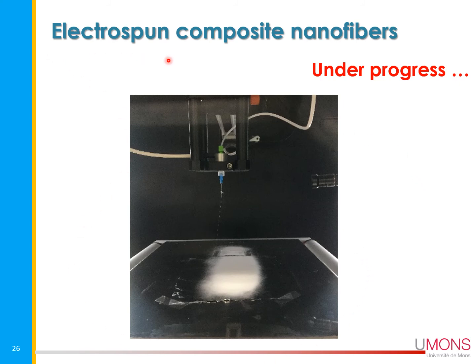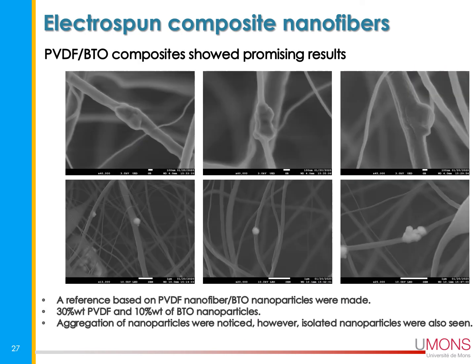Some aspect that we are continuing now, and this is what Kyung is doing for the moment, is to make some electrospun nanofiber. The idea is to add some barium titanate into the fiber. He started to use a PVDF BTO because we know that PVDF is well known with promising results with those nanofibers. So this is the SEM measure. You can see some aggregates of BTO along those fibers.